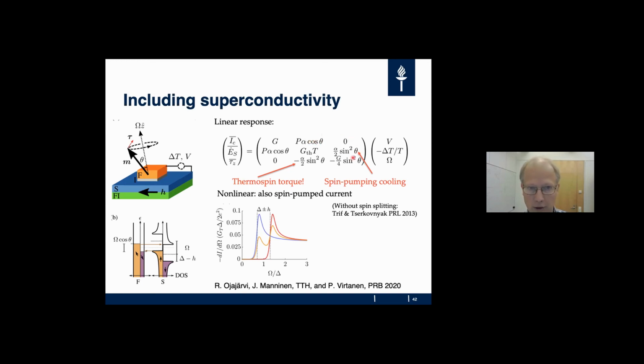But now as new terms, you have a coupling between magnetization precession and heat current. How this shows up is that a temperature difference would give rise to a torque, or the magnetization precession at frequency omega would drive a spin cooling or heating, depending on the direction, on the sign of alpha.